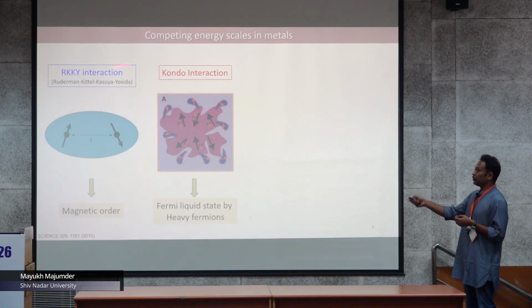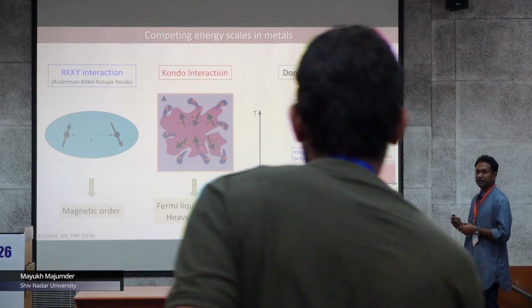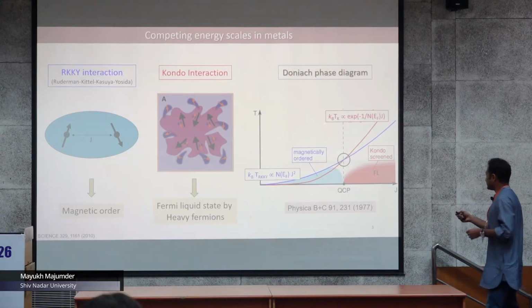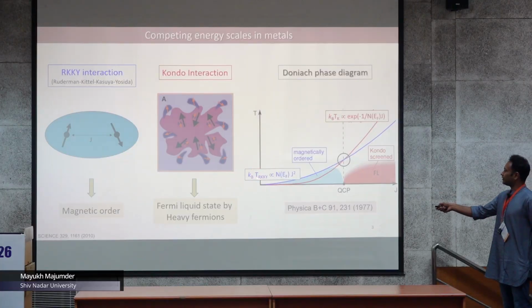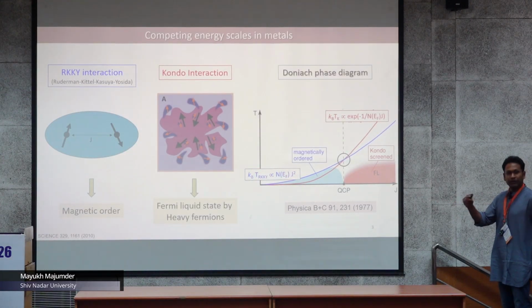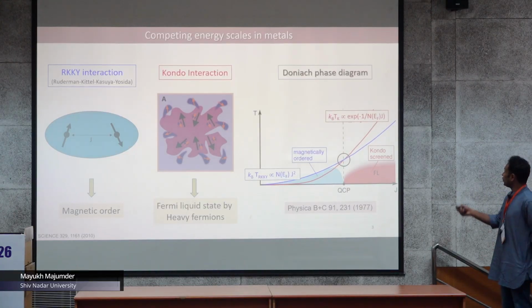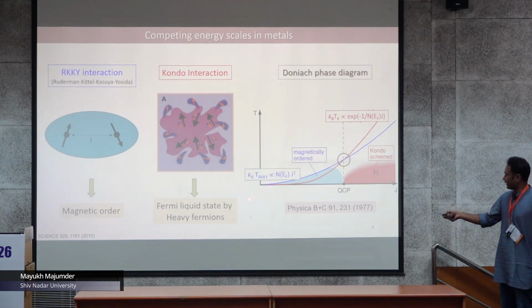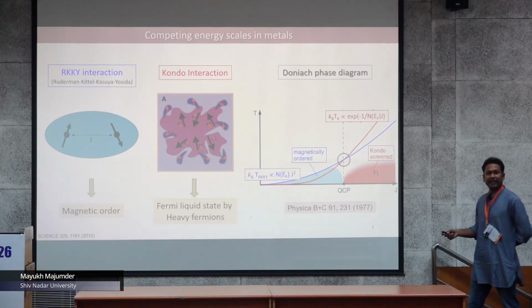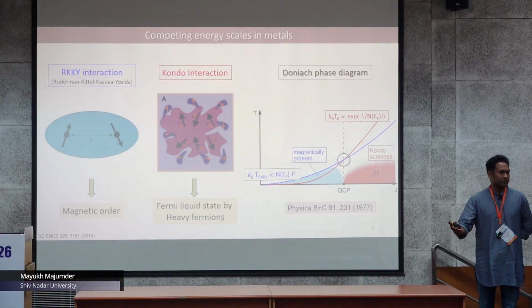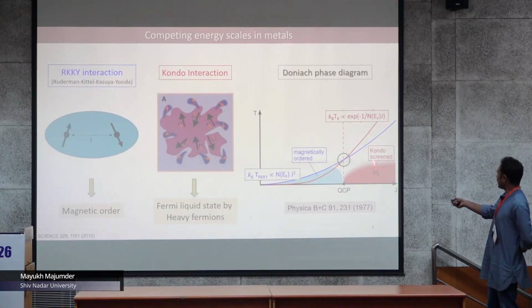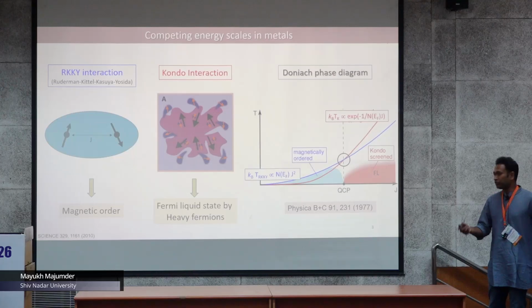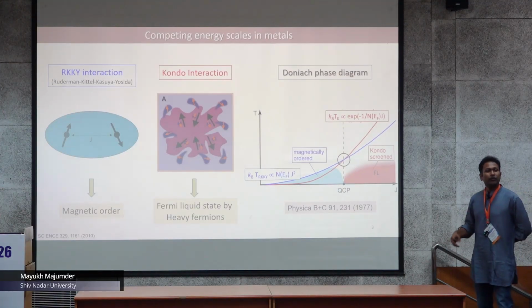Now, of course, this kind of competition was nicely described by the Doniach phase diagram. As you can see here, the main point is that the RKKY scale behaves quadratically with the coupling of the 4f electron with the conduction electron, whereas the Kondo scale follows an exponential behavior. As a result, for low values of J, the RKKY scale wins over the Kondo scale and you have a long range magnetically ordered ground state. Whereas for high values of J, the Kondo scale wins over the RKKY. As a result, you get a Fermi liquid state.